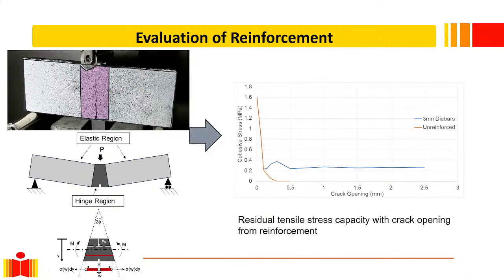What is the residual stress that the steel bar is providing? If you see the orange line over there, that is the residual stress of concrete by itself as it's fracturing. The top of where the curve intersects the graph, the cohesive stress at zero crack opening, is the tensile strength. As you start opening the crack, for concrete, the cohesive stress steadily decreases and comes down to zero. But when you put a steel bar in there, you are able to get a little bit of residual stress from this tiny little steel bar sitting there.